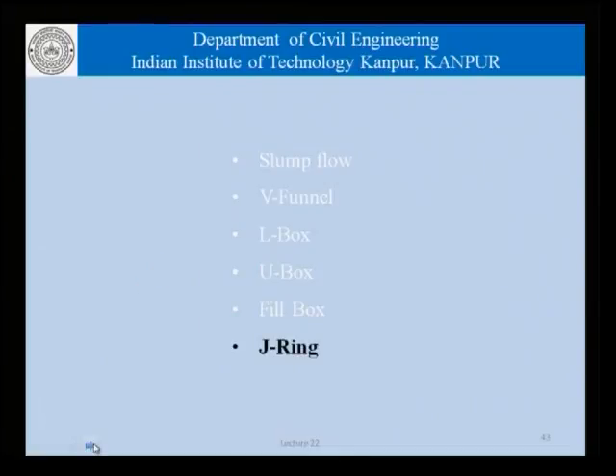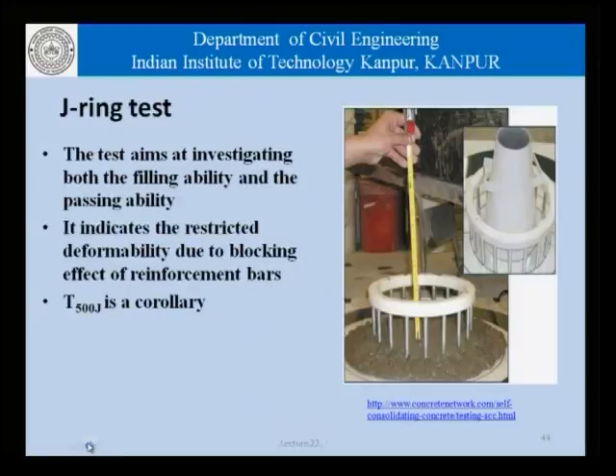Last of all, in this series of tests that we are talking about, let us talk a little bit about the J-ring. Now, the J-ring test aims at investigating both the filling ability and the passing ability at the same time, and indicates the restricted deformability due to blocking effect of reinforcing bars. In a manner of speaking, the J-ring is a combination of the slump flow kind of test with the added complication that the concrete is required to flow through this added cylindrical contraption which has these reinforcing bars and gaps in the bars.